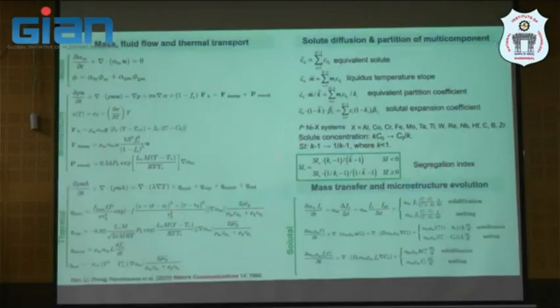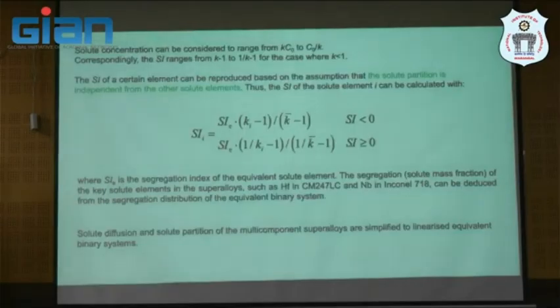Next thing we want to do, we try to solve this big equation here, incorporating the solute transport as well in the multi-component system. That means for the different nickel-based superalloys, you do a pairwise calculation for each system coupled with available thermodynamic data, so that you can extract the solute concentration and these partition coefficients, K, that I will talk a little bit more about later, linked with process conditions. And then you use this to develop understanding of how the microstructure evolved. And this solute concentration is in the range of kC0 to C0 divided by k here.